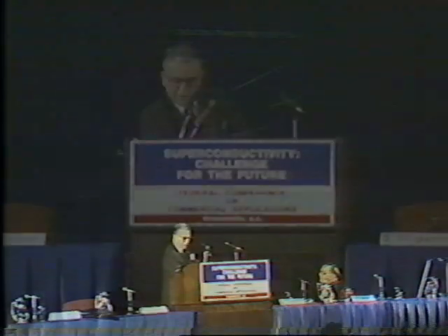And you see that while the normal state resistivities vary enormously between these various rare earths, neodymium, samarium, europium, erbium, dysprosium, and so forth, I won't read them all, the actual critical temperature of the superconducting material is close to the same point. It's a very interesting phenomenon. I think this gives us some flexibility in the technology because we're not restricted to one single compound. I understand that the Chinese have already successfully made a high TC superconductor using mischmetal, which is a mixture of rare earths, which is found in the ground in China, I gather in abundance.